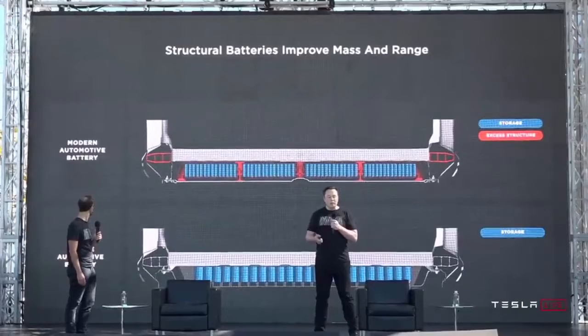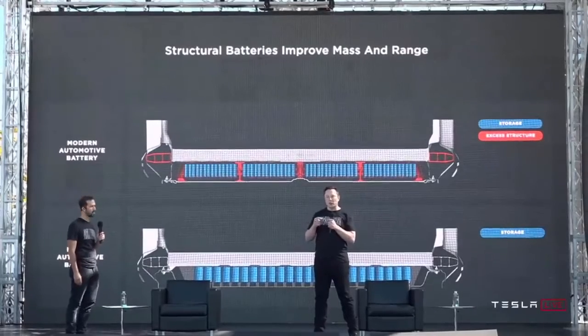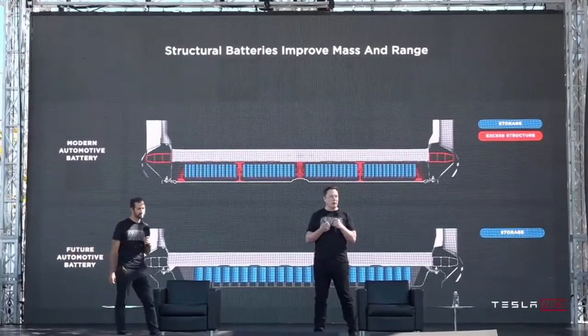It also allows us to pack the cells more densely because we do not have intermediate structure in the battery pack. Instead of having just a filler that is a flame retardant, which is currently what is in the 3 and Y battery packs, we have a filler that is a structural adhesive, as well as flame retardant. So it effectively glues the cells to the top and bottom sheet. And this allows you to do shear transfer between the upper and lower sheet.